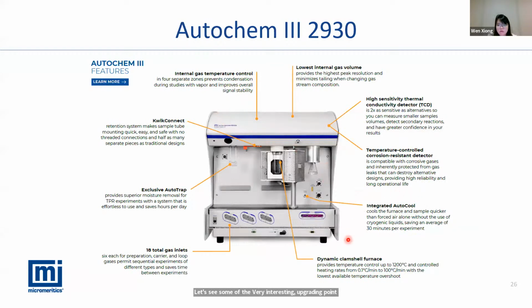Let's see some of the very interesting upgrade points here. First one is our AutoCool on this corner. The new AutoCool is an integrated gas feeding system, which can rapidly cool the sample tube from high temperature to room temperature. Before loading a new sample or doing an experiment, sometimes we have to pre-treat the sample at high temperature and then cool down to do the analysis. So the AutoCool can save 30 minutes compared to the old 2920, and the AutoCool requires no liquid or external support. It works just by voltage for us to do the cooling.